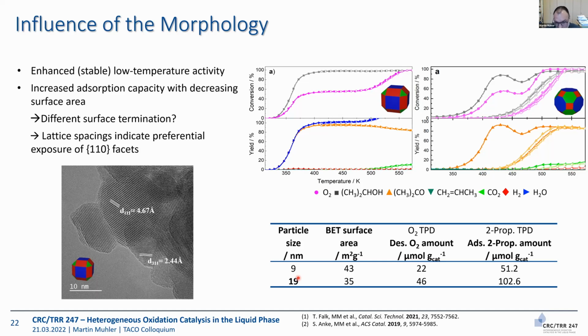In metal catalysis, you would go the other way. Typically, you go to smaller and smaller particles. Here, it's really going to huge ones, which we got again from Stefan Schulz's group. Having larger nanoparticles, of course, the specific surface area is lower. But when we perform the oxygen TPD experiments or the 2-propanol TPD experiments, then we realize we can adsorb much more. That means the total surface area is lower, but what is exposed is more reactive.